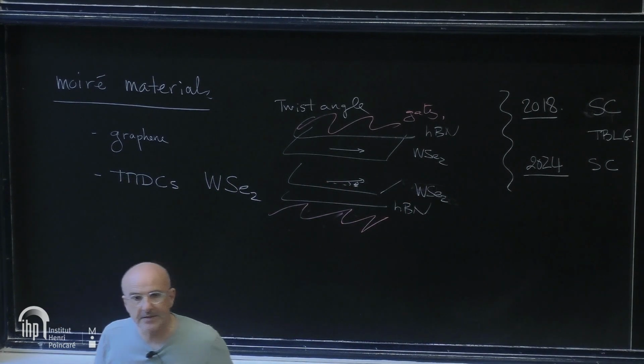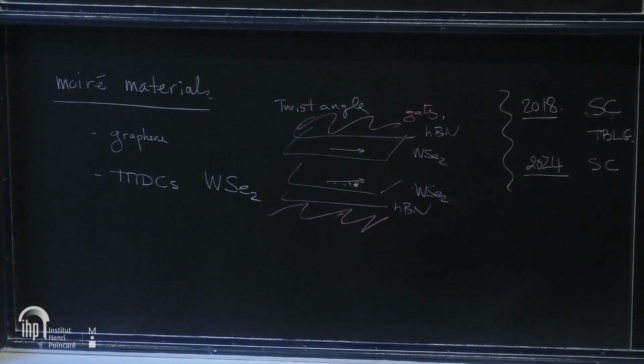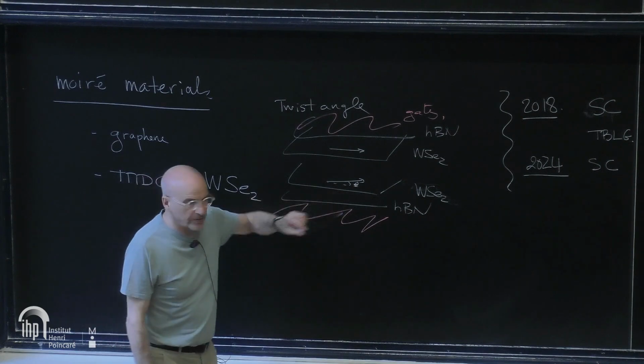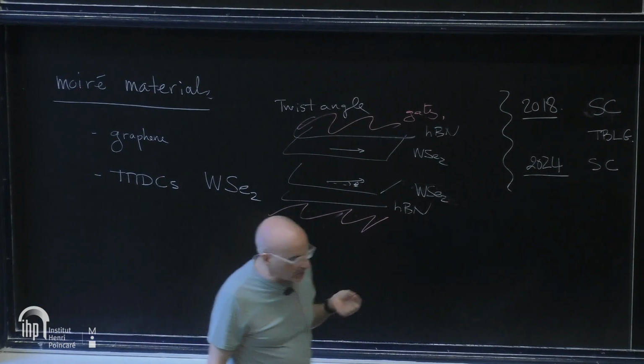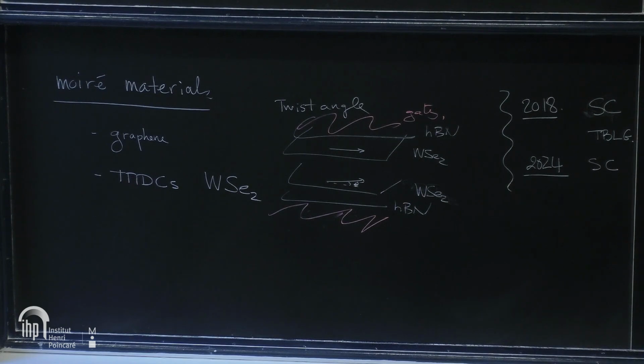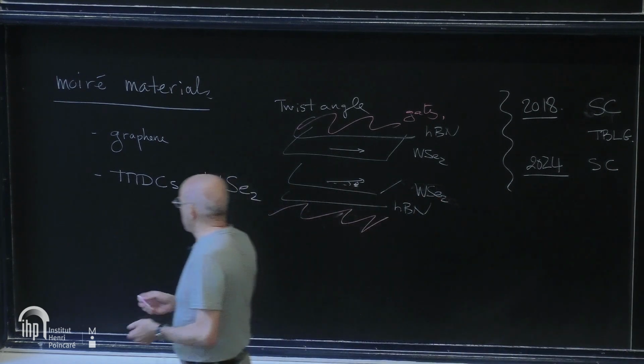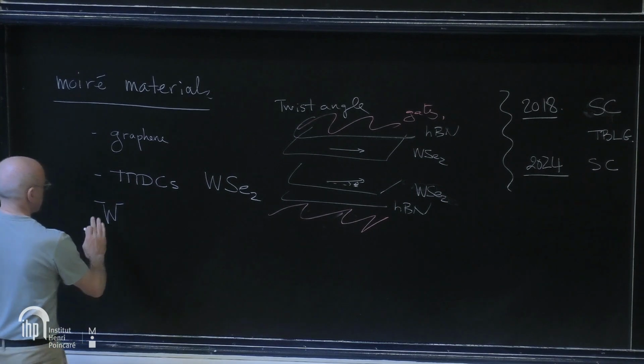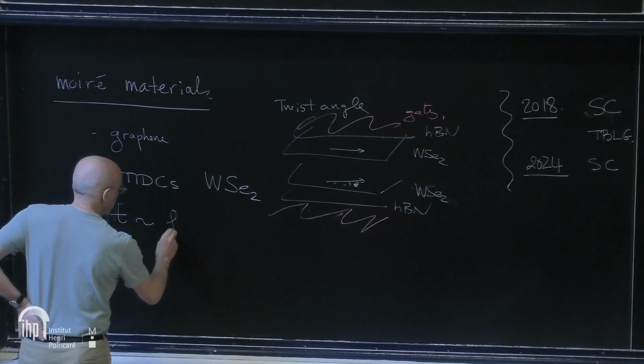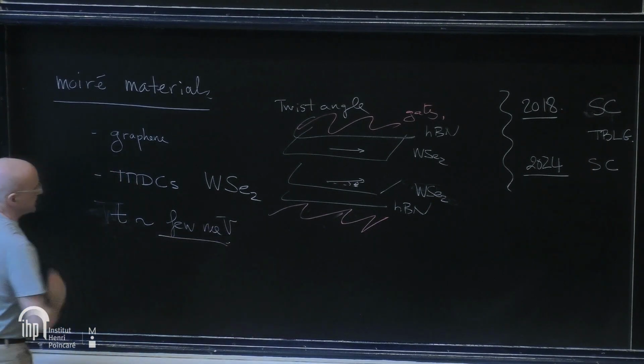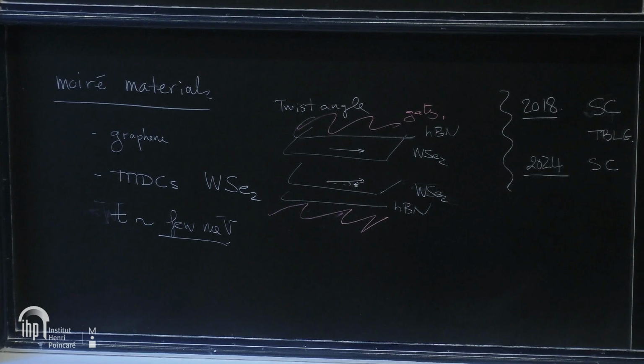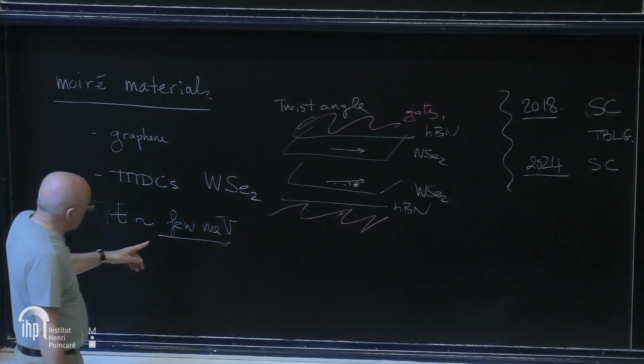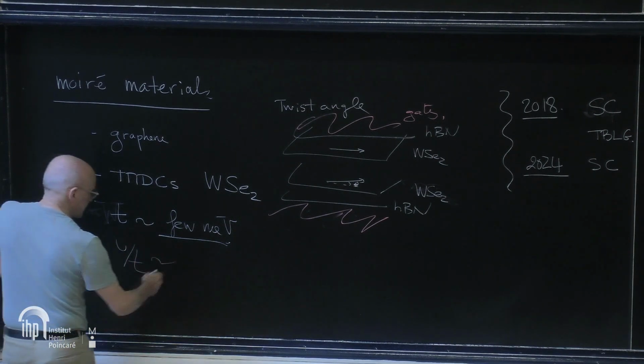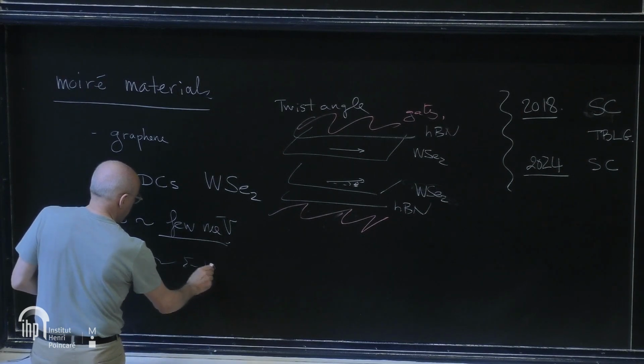They lead to very narrow bands. This is the theoretical proposal of Bistritzer and MacDonald, which suggested that by tuning the twist angle, you can engineer very, very narrow band systems. And when I'm talking about very narrow bands, I'm actually talking about hopping amplitudes, which can be on the milli-electron volt scale. So bandwidth here at, say, the magic angle, well, there is, say, t, can be a few meV. So you see, this is 2 or 3 orders of magnitude smaller than what you have in the transition metal oxides. So that U over t is, again, tunable, but say in the range of 5 to 10 maybe.